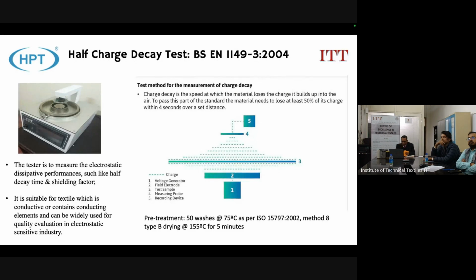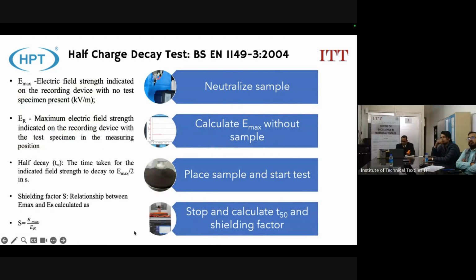Charge decay test. We have been playing with this kit for the last 2-3 months, and we have learned a lot. And the principle is very simple. We have a voltage generator. We can go up to 1200 volts. Without a sample, we are checking the maximum electric field. And once you put the sample, then you are checking the electric field. So the maximum electric field is measured without the sample, and then we put the sample and check the reduction in electric field.